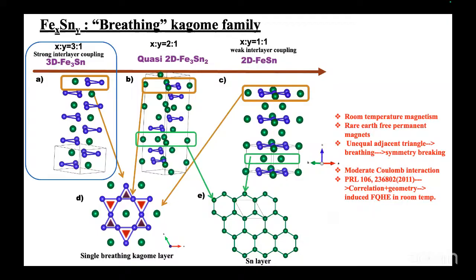But what is the difference quantitatively between these triangles? Like 1%, 0.1% or something in the size of this structure or motifs? In percentage, I don't know, but the bond length, if it is 2.52 and this is 2.59 angstrom, so not much. But in terms of some effective hopping, it would make quite a difference. Yeah, it's more than 1%.